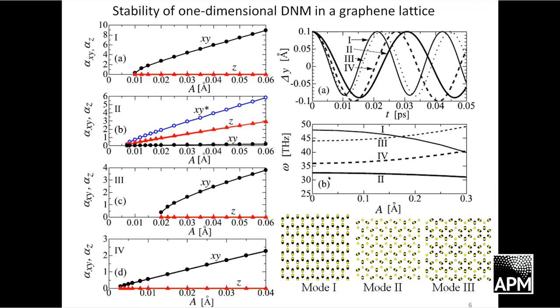We also analyzed the amplitude-frequency dependence for all four modes. For mode number two, frequency almost does not depend on amplitude — it behaves almost like a linear mode because of its sparse pattern. For mode number one, frequency decreases with amplitude because the pattern looks like atoms sliding along each other, so they don't encounter obstacles. For modes three and four, we see a moderate increase of frequency with amplitude, indicating hard-type anharmonicity and the possibility of creating discrete breathers based on those modes.